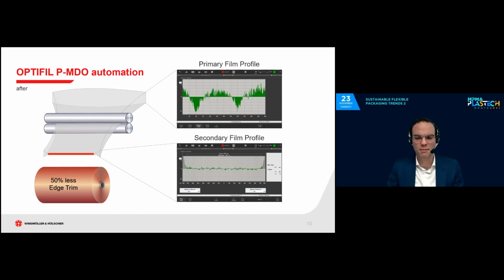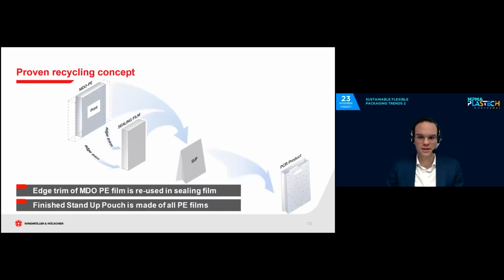The know-how around PMDO automation grows more and more with every machine that we have in the field and every customer trial that we run in the lab. The technology has been around now for more than 8 years, and we are continually improving the algorithm behind it. And of course, to close the loop, as mentioned before, this edge trim, which is unavoidable, can be regrinded and then used in the sealing film. And then the stand-up pouch is fully made of monomaterial, and we can recycle it again and use this regranulate as post-consumer recycled material for products like shopping bags, waste bags, or collation shrink film, which we have done so far.